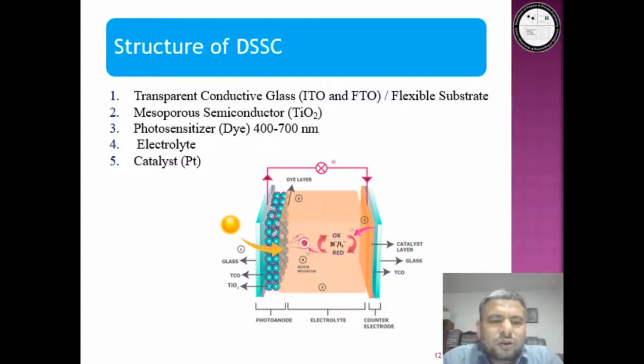The function of the electrolyte is to regenerate the dye after it injects electrons into the conduction band of the semiconductor. However, the long-term stability of DSSC depends on the properties of the electrolyte. Similarly, another important component of the DSSC is the catalyst. Its function is to accelerate the reduction reaction at the counter electrode for the regeneration of the electrolyte. An optimal counter electrode should possess good catalytic activity and high conductivity.